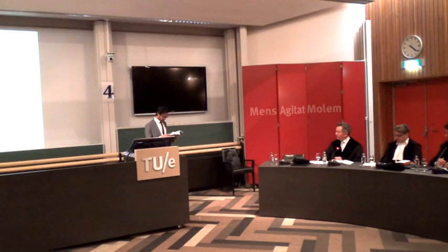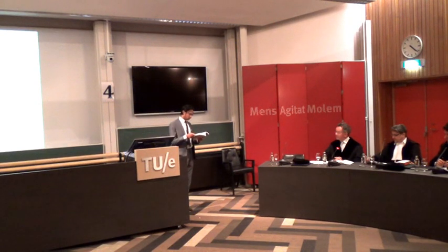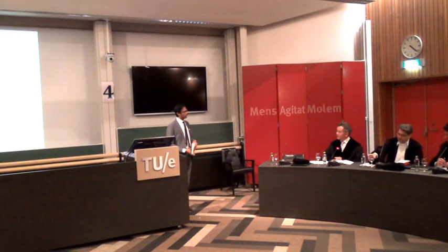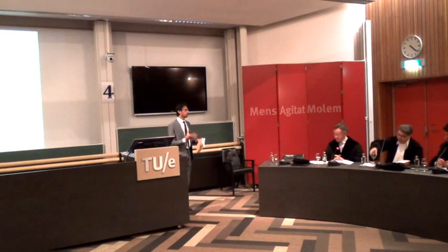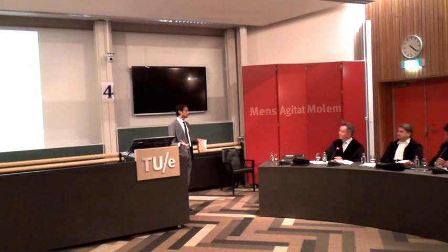Thank you very much for your question. Yes, I calculated the weight average length and diameter because the CNT population which I'm using is polydispersed. There are many short CNTs and many long CNTs also. So I want to give weight in the volume fraction, because if I'm using long CNTs, I believe they have more volume than the short CNTs. At the end what we are talking about is volume, how much volume we are adding with the short CNTs, how much with the long CNTs. So I want to give weight for that. That is the main reason why I've gone for the weight average, not the number average.